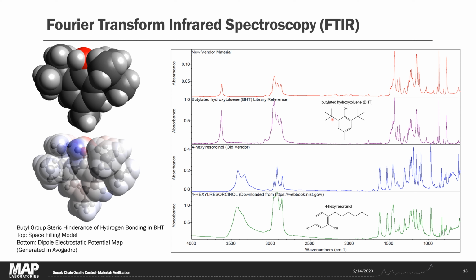And one other really interesting thing about BHT is this really narrow, spiky OH stretching peak, oxygen-hydrogen stretching. Usually when you're looking at something like cellulose or water or alcohol, the OH stretching will be broad like this. And that's from hydrogen bonding. Hydrogen bonding is when the positive dipole of hydrogen is attracted to a negative dipole, often oxygen. And it basically stretches the bond a little bit. They're electrostatically attracted, and that bond stretching is represented in the FTIR as a widening of the peak.